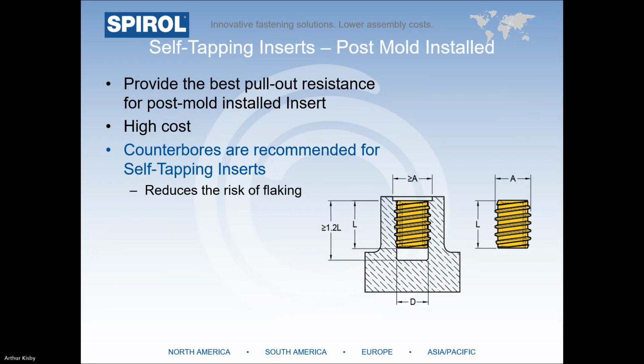Notice the external thread on the self-tapping inserts. This type of post-mold installed insert is actually threaded into the hole after the plastic cures. The external threads are designed with a thin profile to minimize stress in the plastic, and a relatively coarse pitch to provide maximum plastic shear surface to resist pullout. As a matter of fact, these provide the best resistance to pull out of any of SPIROL's post-mold installed inserts.